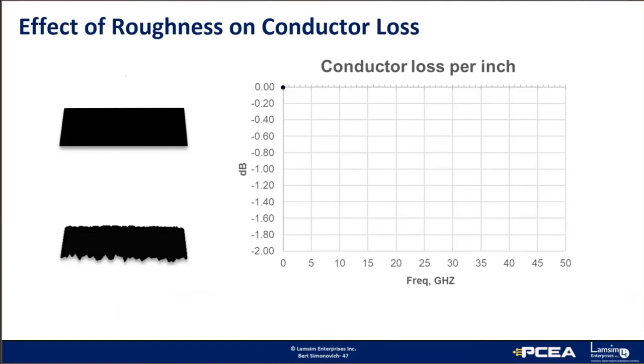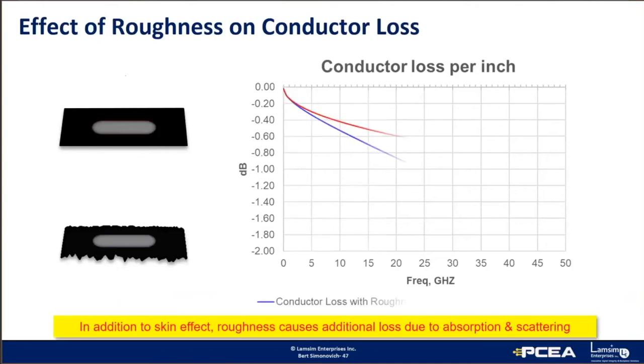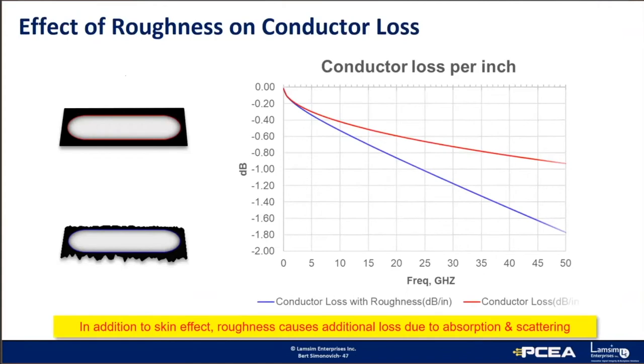At DC, current is uniform through the cross-section in both of these cases. But as you can see, in addition to skin effect, the roughness causes additional loss due to absorption and scattering as the wave propagates along the transmission line.